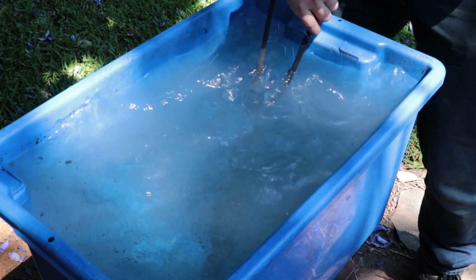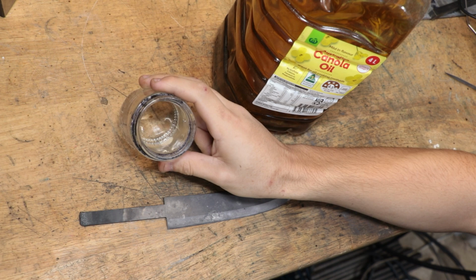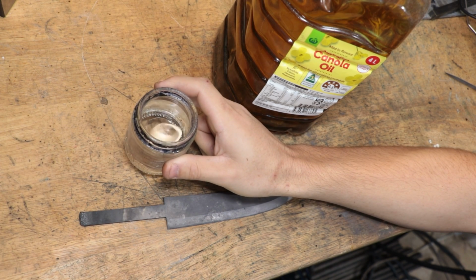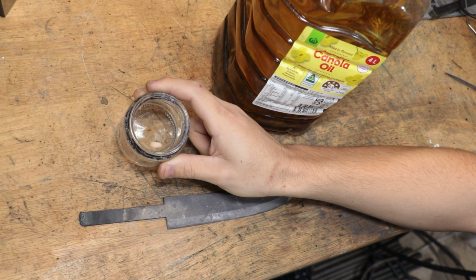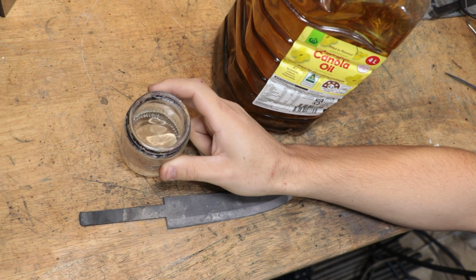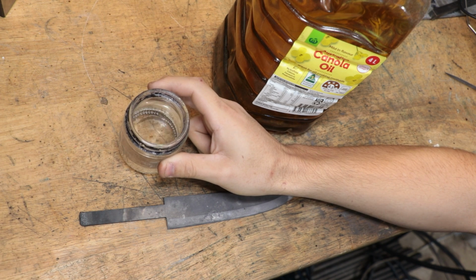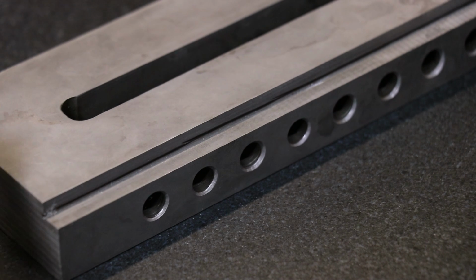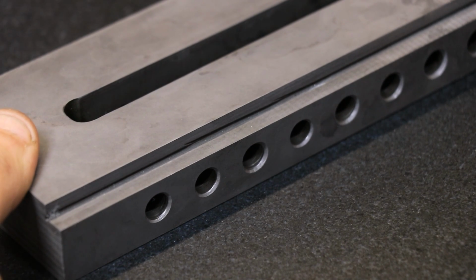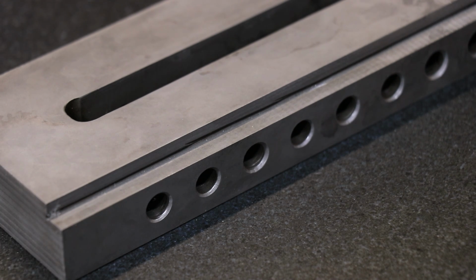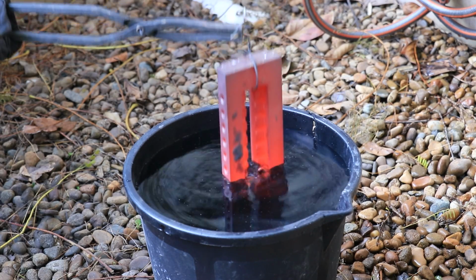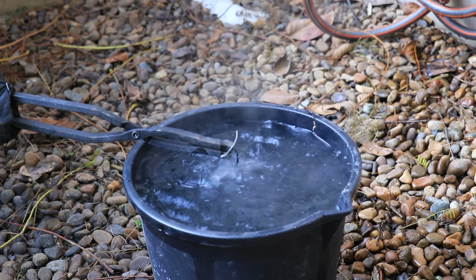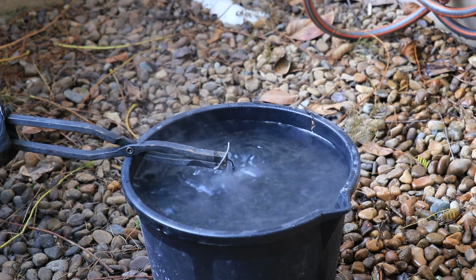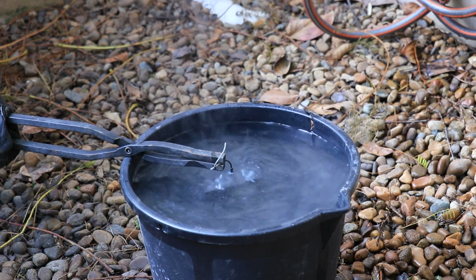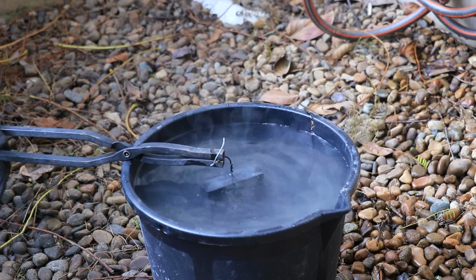The big downside to water though is that because the part cools down so quickly, there is a big risk of the part cracking as it cools down, contracts and becomes more brittle. And especially once parts become complex with thin walls and internal cavities, then you can have a lot of issues. As the part cools down, you also want it to cool down evenly, and if it's unevenly cooled, it can cause it to warp. And when you quench in water, there is a huge risk that if the part doesn't cool down evenly, the part is going to warp and distort. And if that already wasn't bad enough, the water will then turn to steam and it will coat and stick to the part and further cause it to cool down unevenly. Now, a 10% saltwater brine can help reduce this, but there's only so much that salt water can do, and you end up using a fair amount of salt to achieve it.